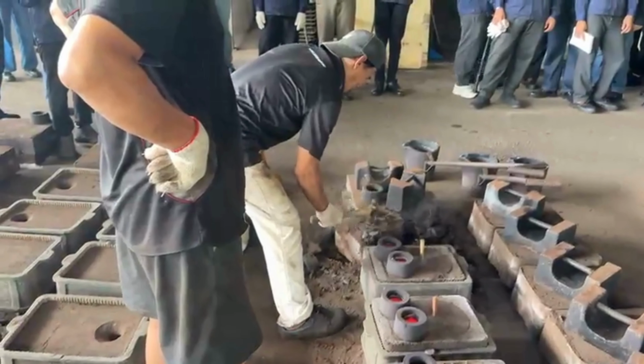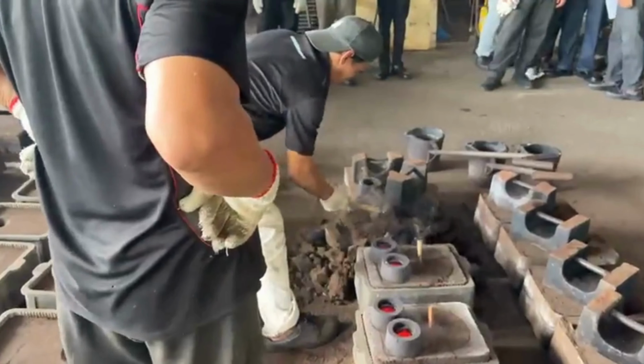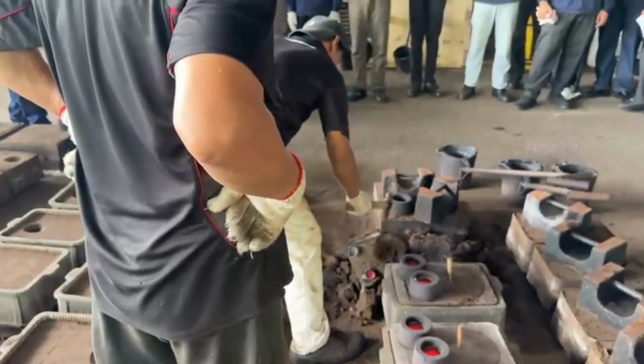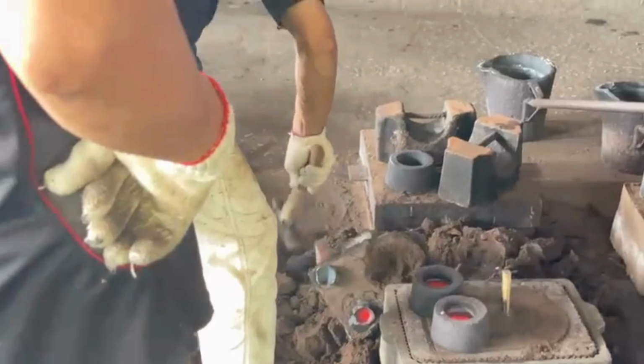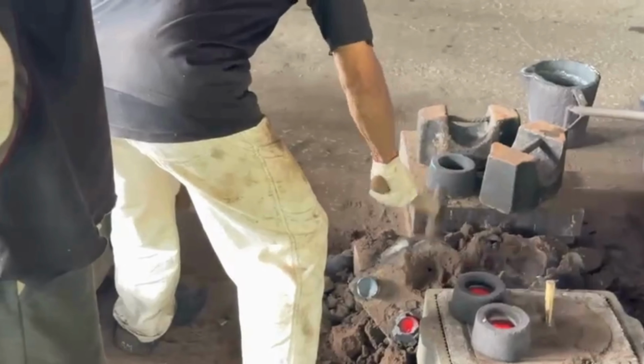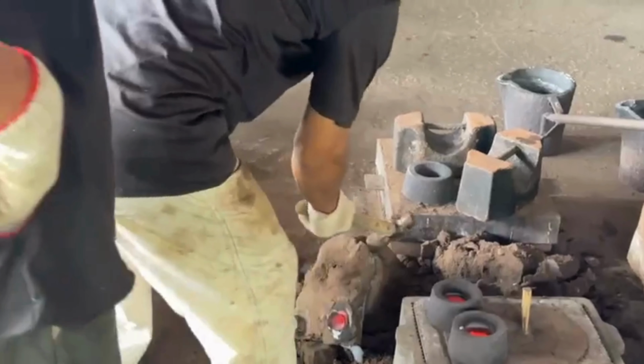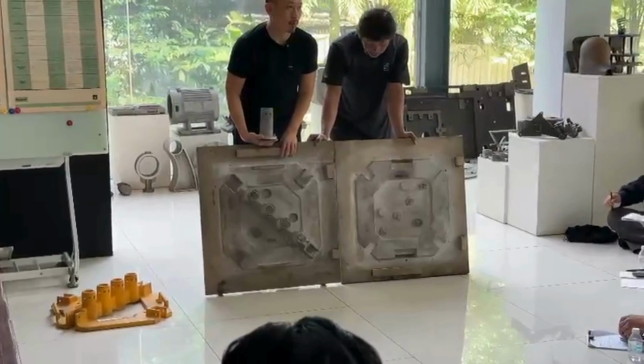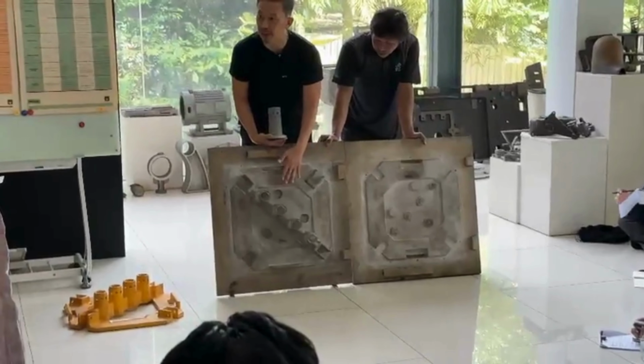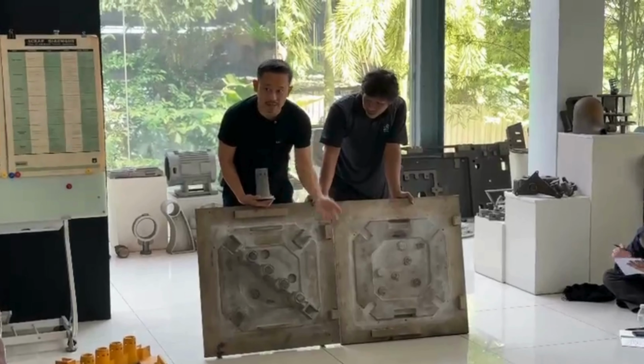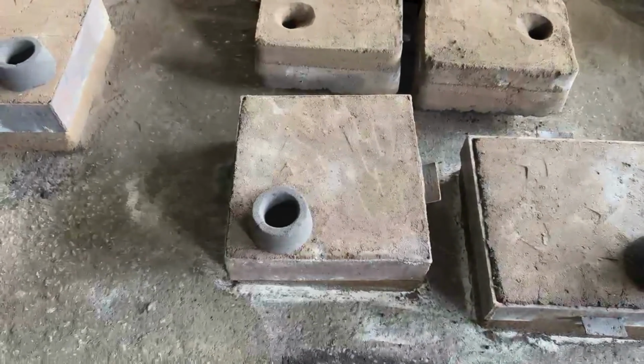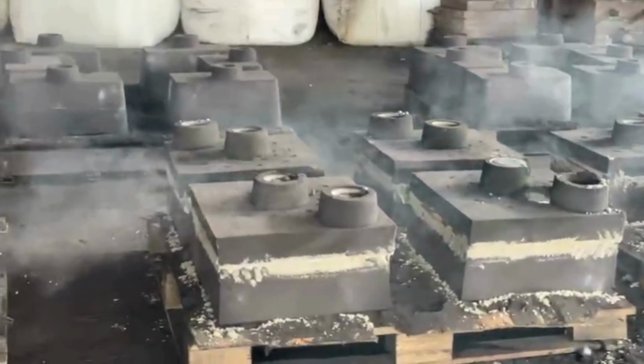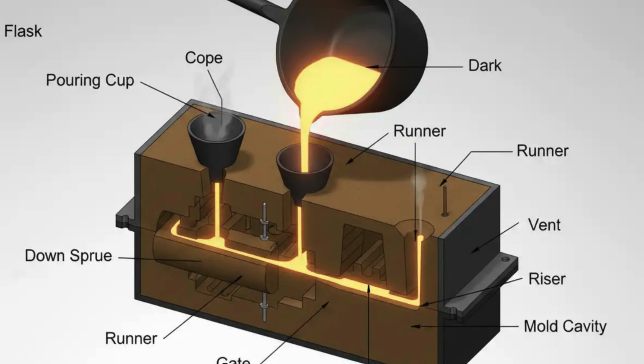To understand why these blowholes were happening on the Sama Mahir line, we carried out a root cause analysis. We found two main causes. First, the moisture content in the green sand was too high. When the molten metal, which is around 1000 degrees Celsius, comes into contact with the dampened sand, it quickly generates a large amount of steam. Second, the mold didn't have enough venting, so the steam and trapped gas couldn't escape. Instead, they became trapped inside the molten metal, and as it solidified, they formed the blowholes we observed.